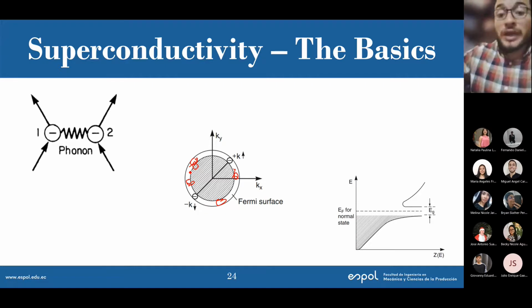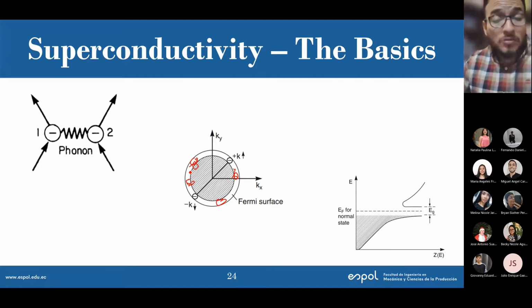So if I have a good conductor in the normal state, it will very likely not form these Cooper pairs at low temperatures, and therefore will not be a superconductor. And that's actually a general rule. If a material is a good conductor at normal temperature, it won't be a superconductor. Whereas if a material is a poor conductor in the normal state, it's very likely, not all of them, but very likely, that it might become a superconductor at low temperatures. Is that clear? Yes, thank you. Okay.